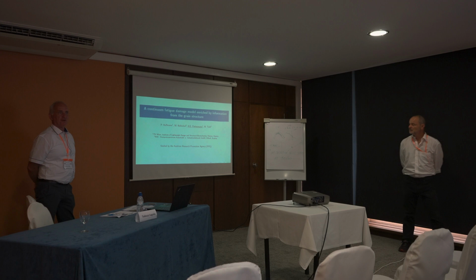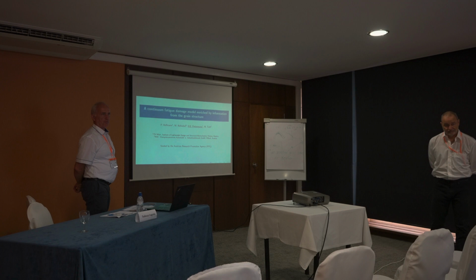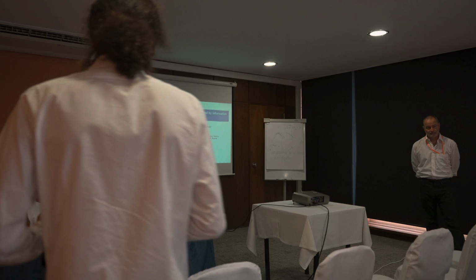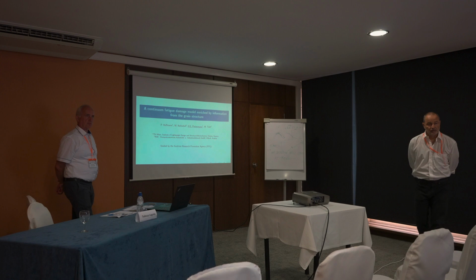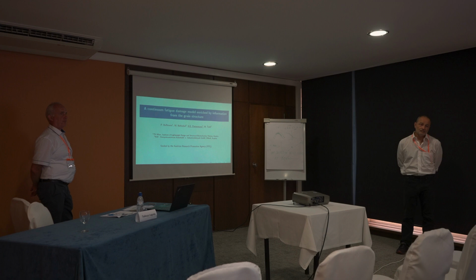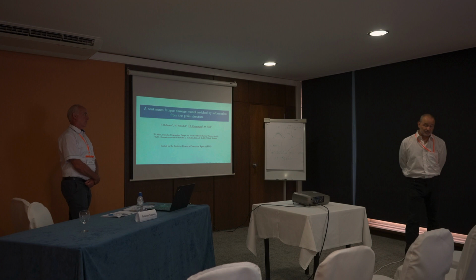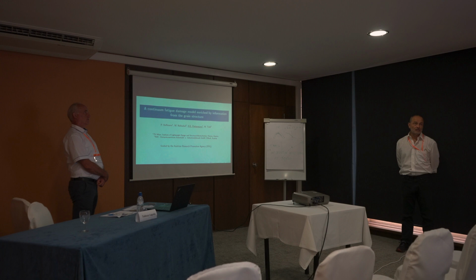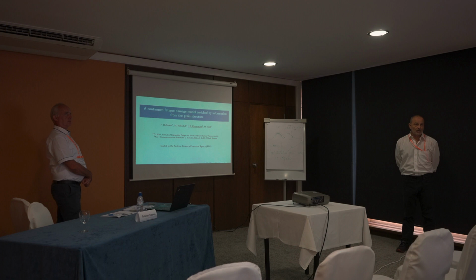Inside the experiment, you see something that you call cracks. They occur mainly on triple points, I assume. It starts there, yeah. And mainly on grain boundaries. Do such cracks also appear within grains, or not? So the typical location where they nucleate is on the triple points, and then they grow and coalesce. I would say, if I remember correctly, most of the cracks then are along the grain boundary.